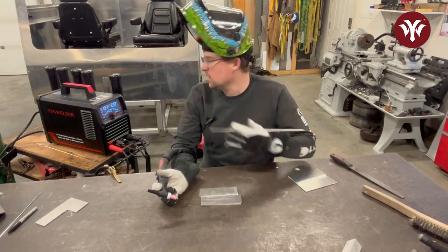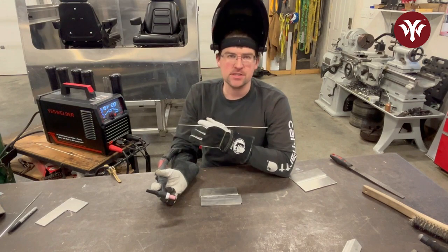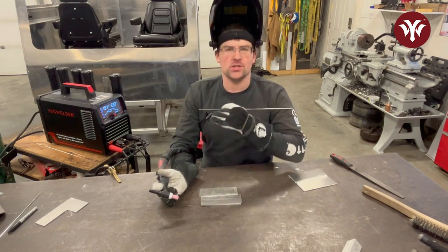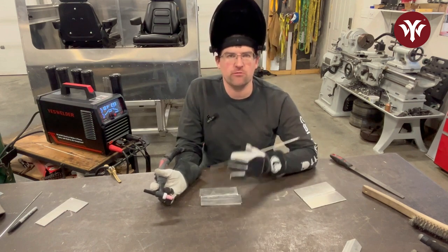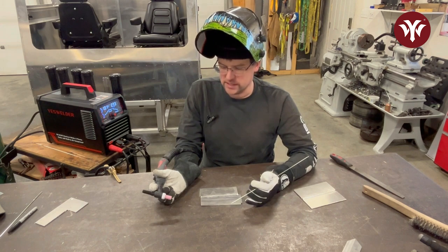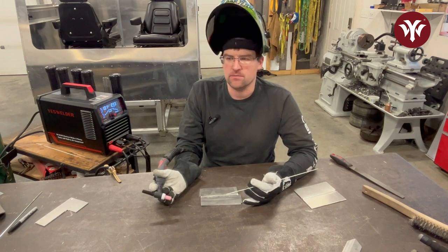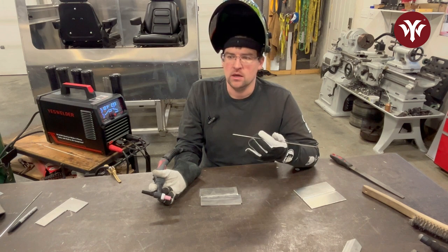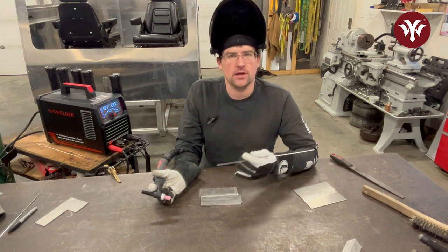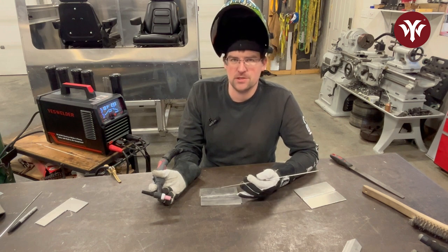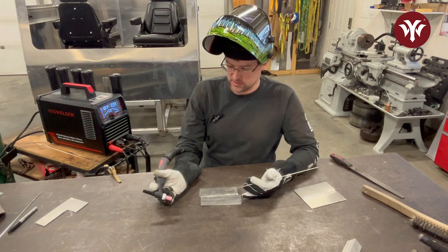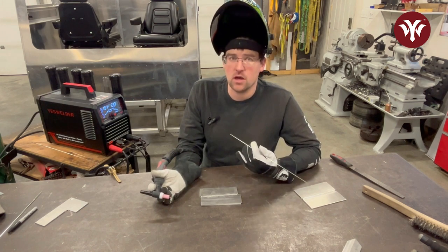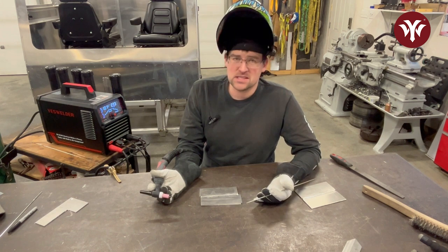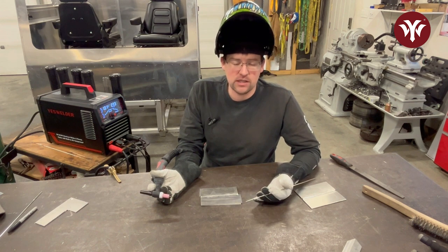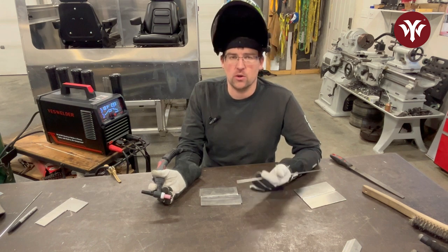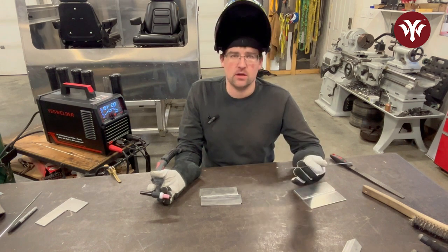Okay, with our coupon ready to go and pulse settings enabled at 0.5 hertz, let's see how many pulses a second that's gonna be. I suspect that's gonna be a little low for the speed I like to weld with, but it really comes down to how fast you can move. The idea, again, with pulse welding is to allow for minimal heat to be put into the part, but to achieve the weld you're looking for. Usually used on thinner materials, but it's not limited to thinner materials. Pulse welding isn't really something I do a lot of, because I'm usually welding between maybe 60 thou to 3/16, and I've just never really felt the need to use it, because I usually do most of the control with the foot pedal myself, but I know people have been asking about it.